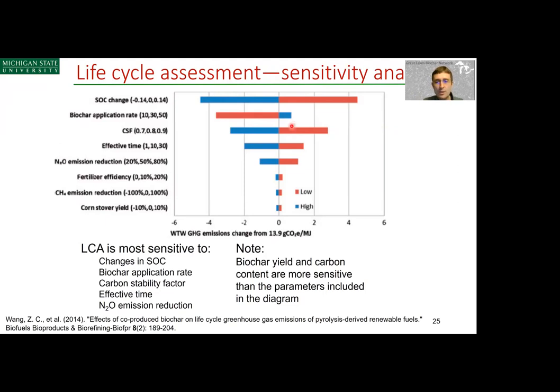If you vary the carbon stability factor, which has to do with how stable the biochar carbon is, 0.8 is the base case value. If you increase that to 0.9, meaning 90% or so of the biochar carbon is stable, then you decrease the amount of emissions as a result.